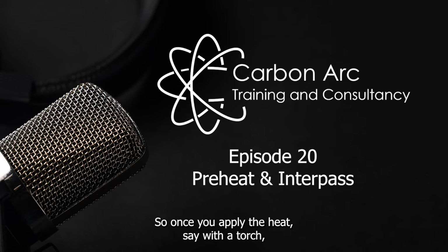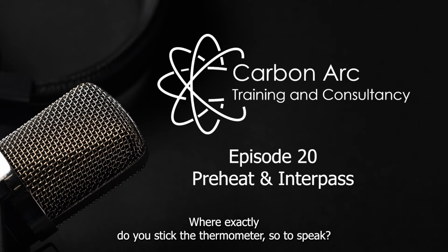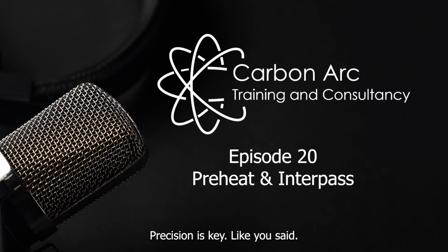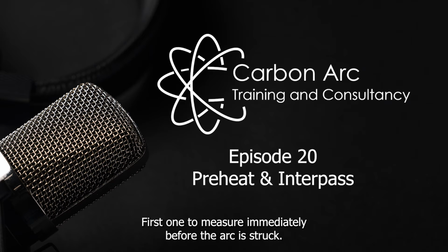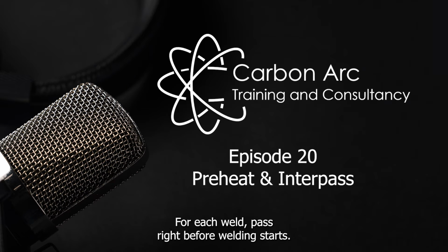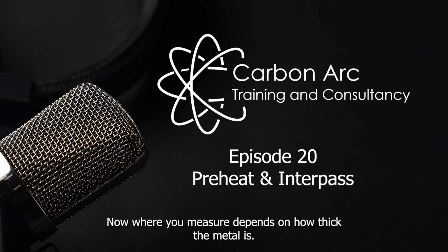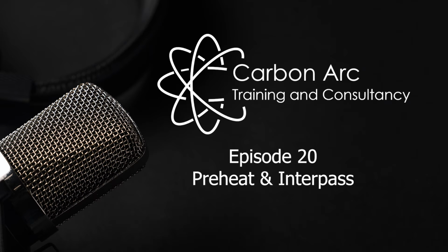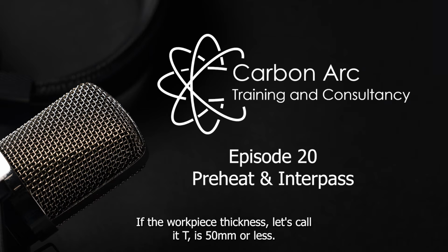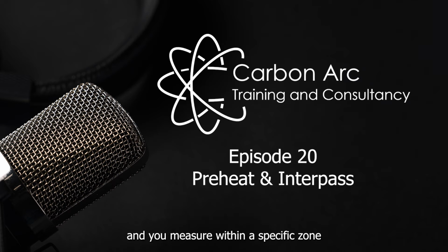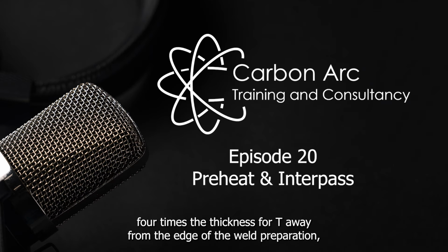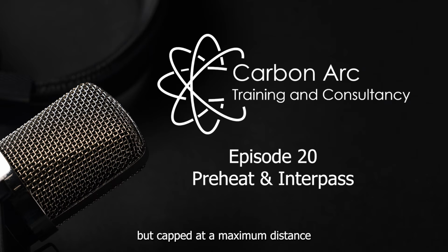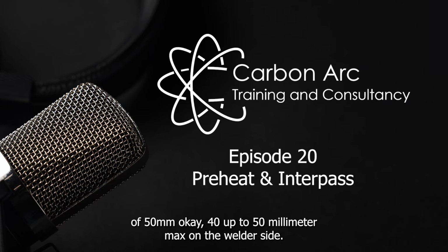So once you've applied the heat, say with a torch, how do you control it and measure it accurately? Where exactly do you stick the thermometer, so to speak? Precision is key, like you said. First, when to measure. Immediately before the arc is struck for each weld pass, right before welding starts. Now, where you measure depends on how thick the metal is. If the workpiece thickness, let's call it T, is 50 millimeters or less, you measure on the surface facing the welder. And you measure within a specific zone: 4T, four times the thickness, away from the edge of the weld preparation, but capped at a maximum distance of 50 millimeters.